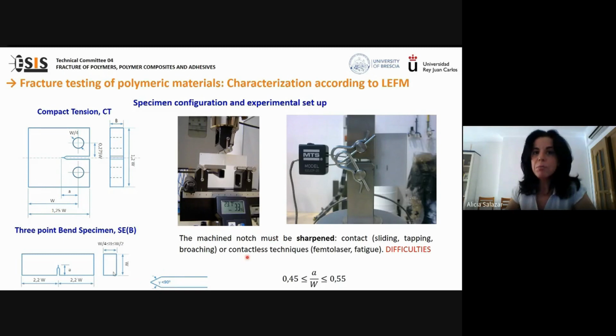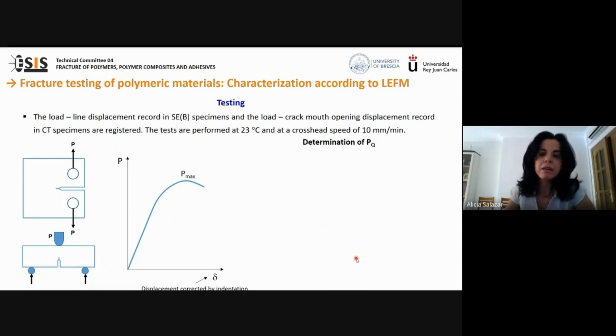The machined notch must be sharpened, and the total final crack length after sharpening must be between 0.45 and 0.55 times the width. Notch sharpening is a very difficult task, and more details will be given this afternoon in the talk Notching for Fracture Testing of Polymers. The test is performed at room temperature and normally at a cross-head speed of 10 millimeters per minute, and the loading time and the loading rate must be noted.